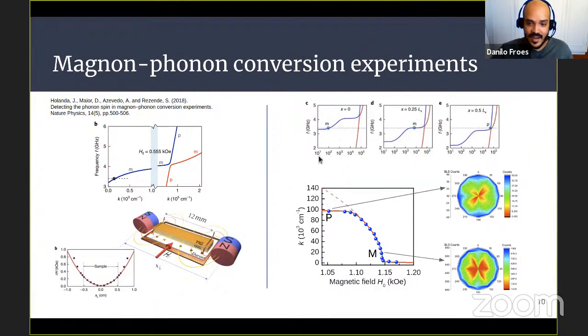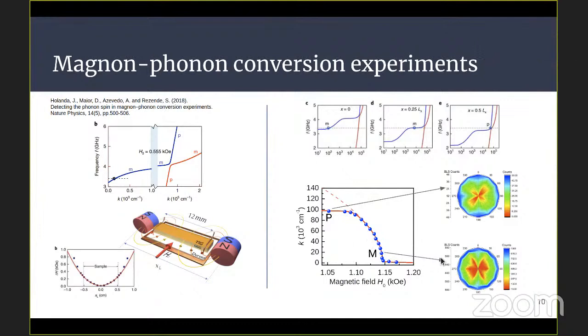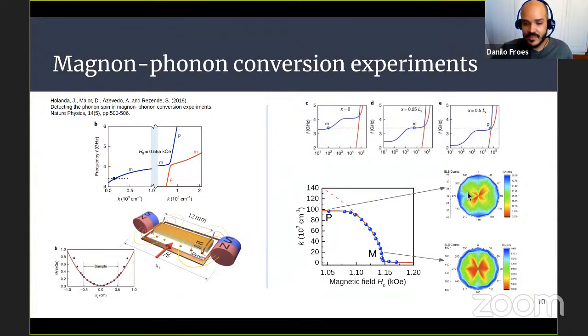And by exciting a magnon-only state, by changing the magnetic field, here we have energy conservation but not momentum conservation, this magnon gradually becomes a phonon. And this here shows that in Brillouin light scattering, you can see that both the phonon and the magnon have a circular polarization. So it indicates that this phonon created this way carries the angular momentum of the magnon. So this was the main work, our main reference for my PhD thesis.